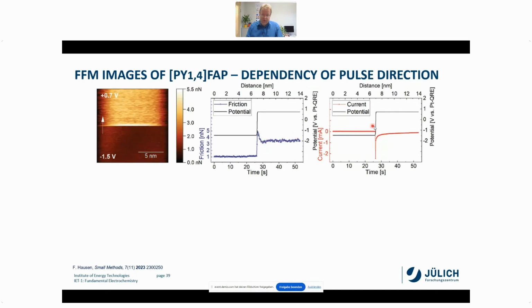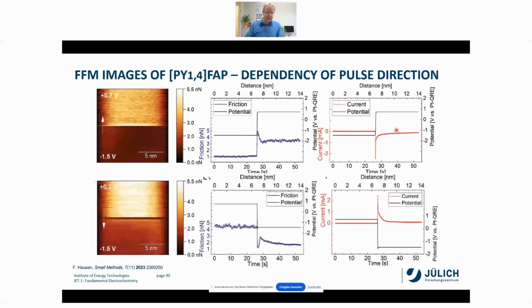At the same time, we can look at the current. So this is the capacitive current we measure here, and we can do that for the other direction as well, switching from positive to negative potentials. And then we look at the friction again. And here we see, after this initial decrease in stabilization, an exponential decay.